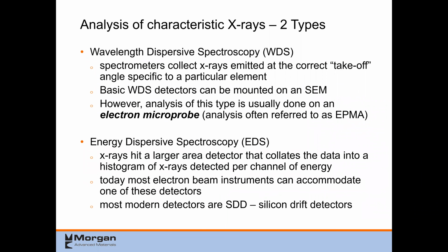Two different types of characteristic X-rays are looked at. Wavelength dispersive spectroscopy is what an EPMA uses. They collect the X-rays emitted at the correct takeoff angle, which is specific to a particular element. There's a crystal inside that has a defined D spacing, so you're basically using Bragg's law in reverse. You already know the spacing, and you use that to back out the proper wavelength so that you can figure out what element it is.